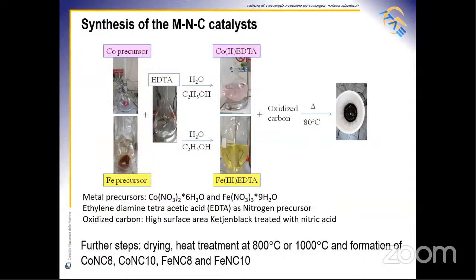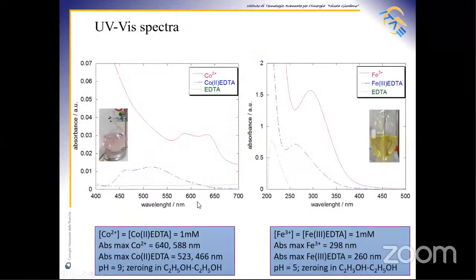The obtained powder was carbothermally treated at 800 degrees or 1000 degrees with the formation of cobalt NC8, cobalt NC10, FeNC8, and FeNC10. The figures compare the UV visible spectra of cobalt EDTA and iron EDTA complexes. For comparison, the spectra of cobalt 2+, iron 3+, and EDTA were acquired at the same experimental conditions.